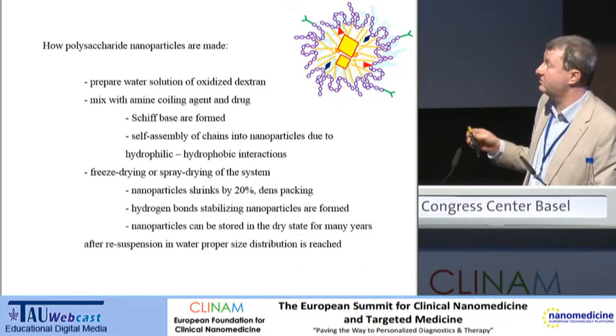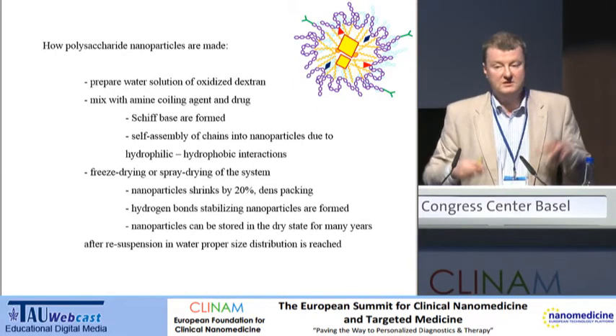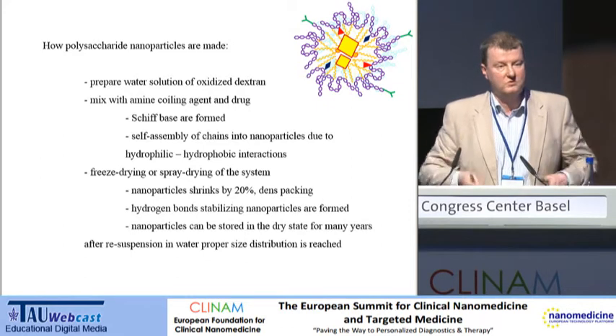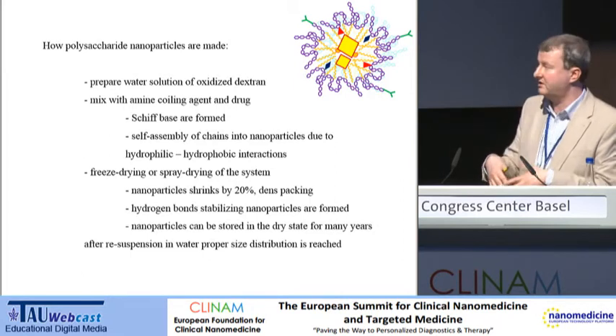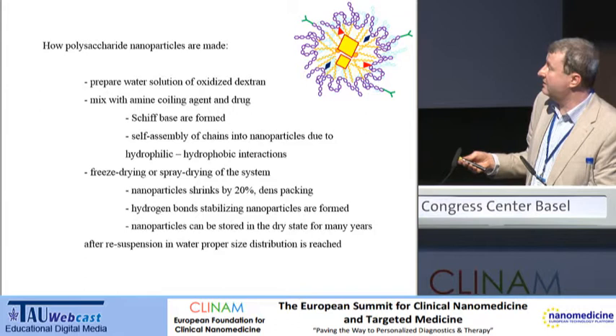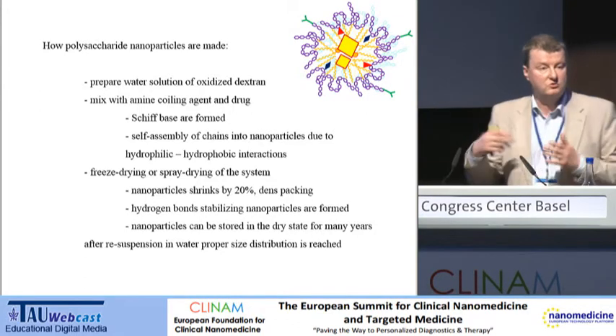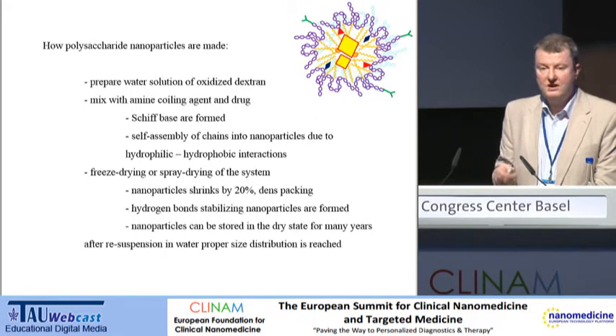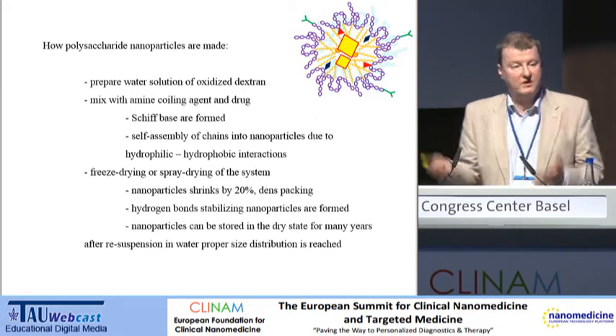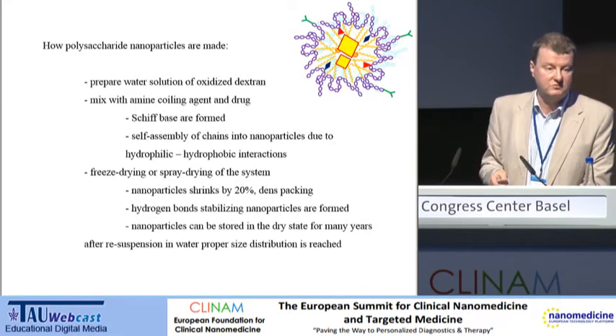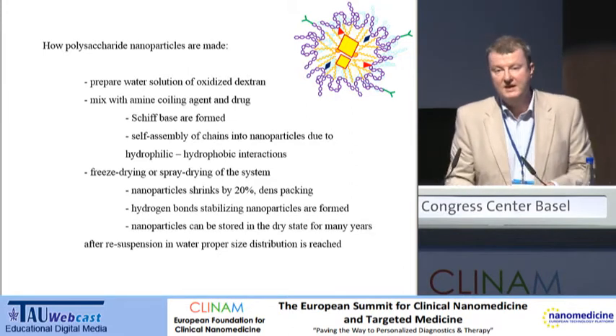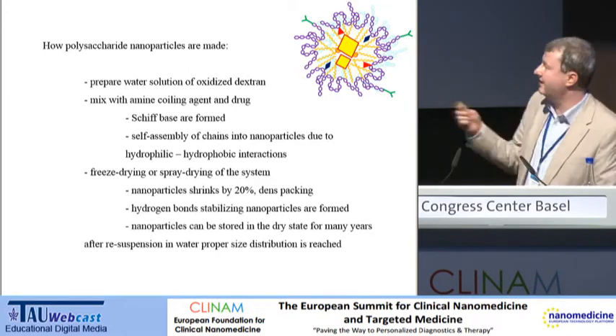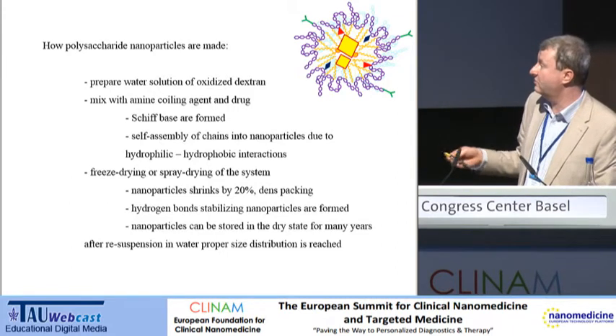Because the second very important step is freeze-drying of nanoparticles. In this moment, we remove water molecules from inside nanoparticles and we allow hydrogen bond formation inside the nanoparticles, which makes them very stable. We observe that our nanoparticles shrink about 20% during lyophilization. We can store lyophilized nanoparticles as a dry powder for quite a long time — the oldest samples we have are older than one year. Simply after adding them into water or saline, the nanoparticles reassemble again with a reproducible size distribution.